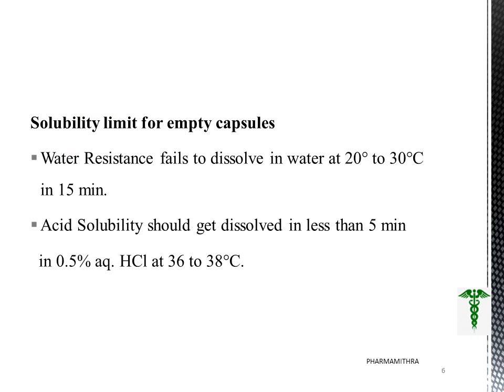Coming to the solubility limit for empty capsules, they should be water resistant, failing to dissolve in water at 20 to 30 degrees Celsius. For acid solubility, it should dissolve in less than 5 minutes. That is, if it is acid soluble, it should dissolve within 5 minutes in 0.5% aqueous hydrochloric acid at 36 to 38 degrees Celsius.